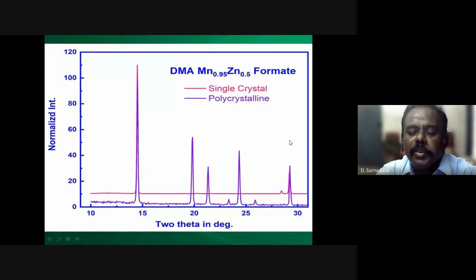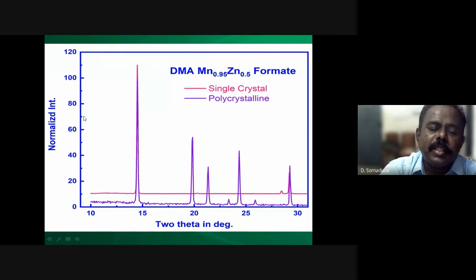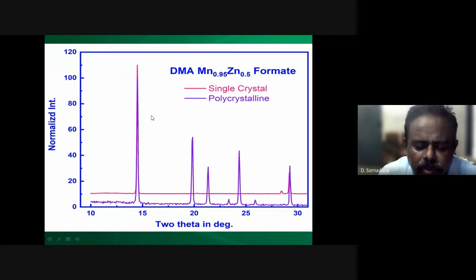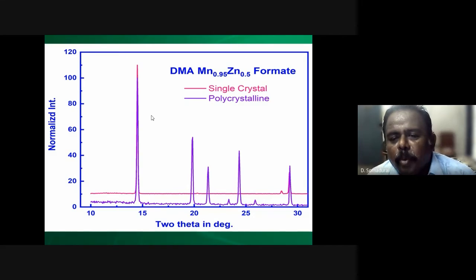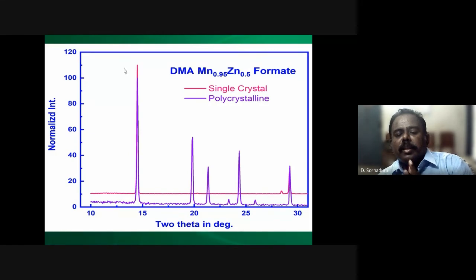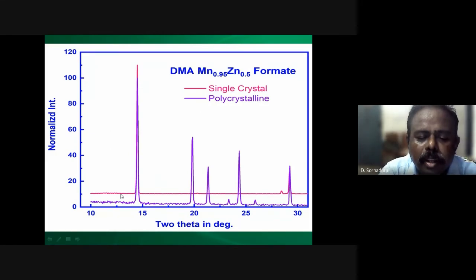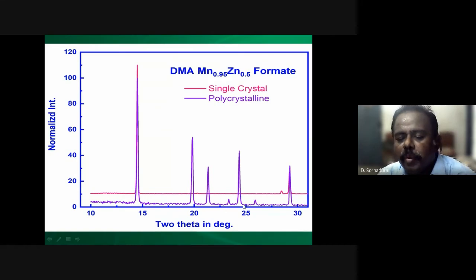Okay, so another powder XRD pattern. This is actually an interesting XRD pattern. This is called dimethyl ammonium metal formate. If you take just the manganese one alone, forget about the zinc here. What is happening? I have taken the crystal and recorded the powder XRD pattern. You can see these two peaks, no? They are well overlapped with the polycrystal material. And these peaks, 1, 2, 3, 4, are also very important.